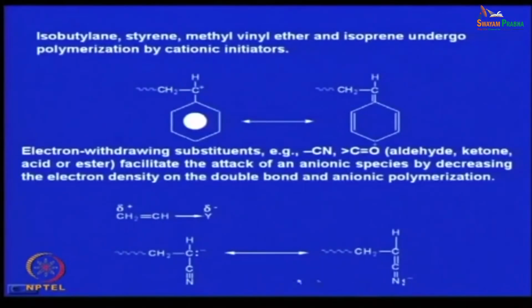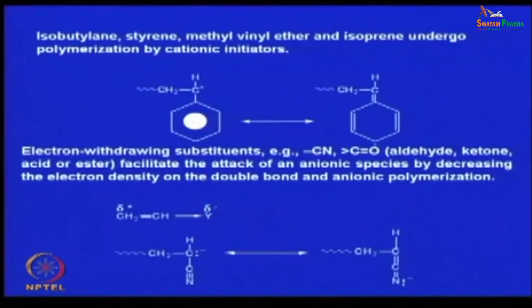In case of acrylonitrile, here you see in this case this CN group is electron withdrawing type. It is withdrawing electron from this pi bond. So, this carbon will be delta positive. This kind of monomer will undergo polymerization by anionic species. Say butadiene can be polymerized by anionic species, anionic polymerization. Isobutylene can be polymerized by cationic species, cationic polymerization. So, this is the situation.